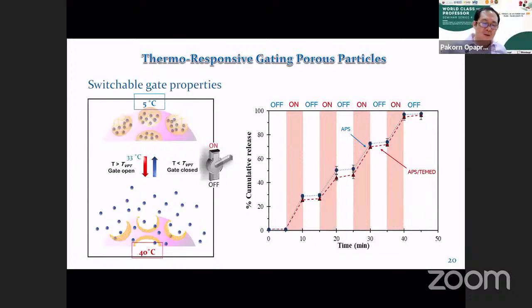On top of that, not only do we look at the normal release behavior of the material, we also characterize the precise control of the close and open mechanism here. So we call this switchable gating properties. What we do is take our materials and lower the temperature to 5 degrees Celsius. By doing this, the pore structure will close and we keep all of the fluorescent dye in the particles. So when we measure the amount of dye that comes out, nothing comes out, so 0%. However, when we increase the temperature higher than 33 degrees, to 40 degrees Celsius,